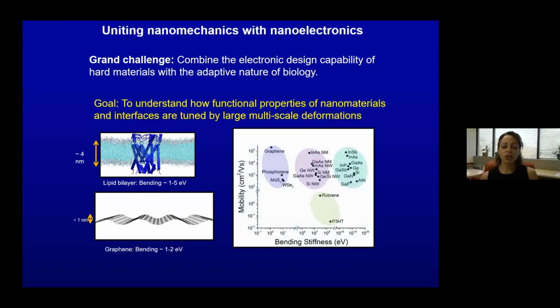And usually there's a trade-off between flexibility and mobility. Biological molecules are not very conductive, so they're not great for electronics, whereas silicon materials are very conductive, or semiconductors, but are not flexible. You can see in this graph that typical silicon, gallium arsenide, hard semiconducting materials have a very high bending stiffness, but their mobility is very high. But now there's a sweet spot with 2D materials like graphene and molybdenum disulfide that have a very low bending stiffness, but also a very high mobility. So these are really an outstanding choice for a new generation of flexible nanoelectronics.